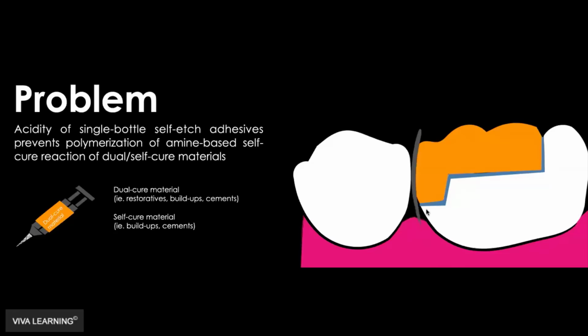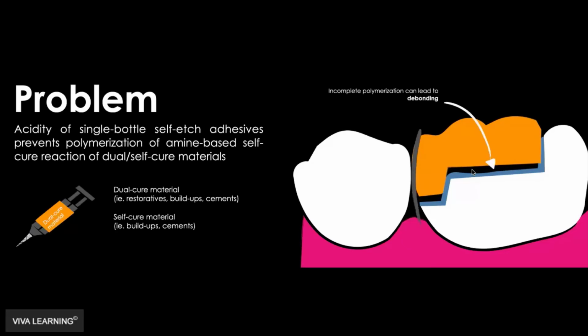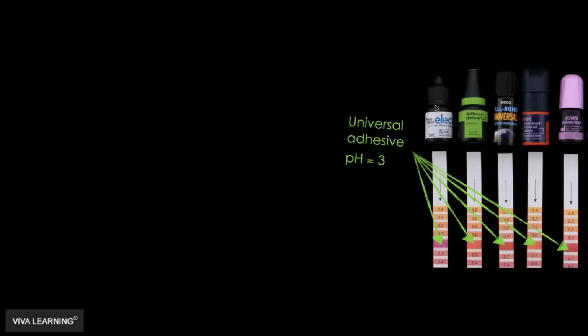And so the acidity of that bonding agent can prevent the polymerization of your dual cure material, so you don't get a bond here and you get a debond, which is a big problem, not good. And like I said, this isn't a niche thing. If you look at these bonding agents here, like Prime Bond Elect, Adhese Universal, All Bond Universal, Scotch Bond Universal, Clearfil Universal Bond Quick, all these universal adhesives that are very, very popular in the market are all slightly acidic. So they're all capable of inhibiting the polymerization of our dual cure material.